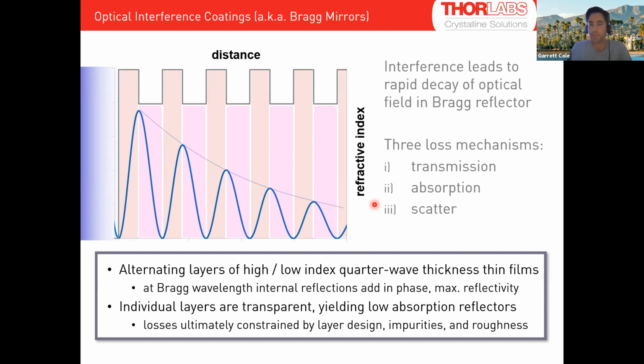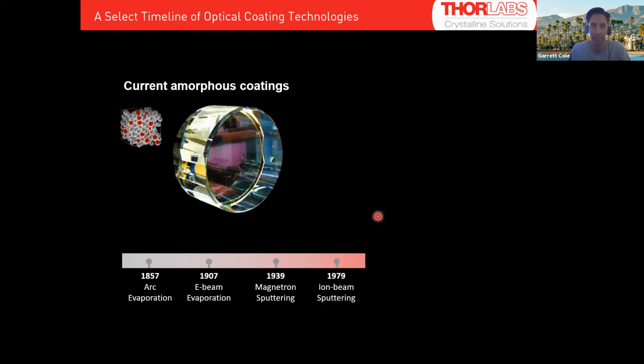Primarily here, we're going to be focusing on minimizing the absorption and scatter. So we want high purity, relatively wide bandgap materials, at least for the wavelength range that we're operating in. And we want to reduce the scatter by making very smooth surfaces with sharp interfaces, good control over surface figure and so on. So that's the basic overview of the mirror structure.